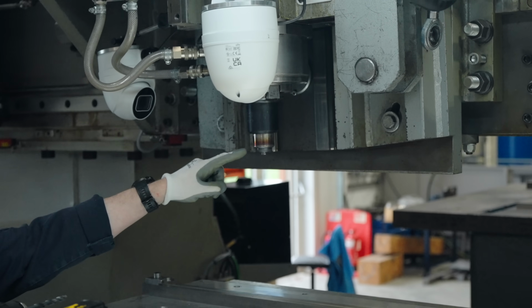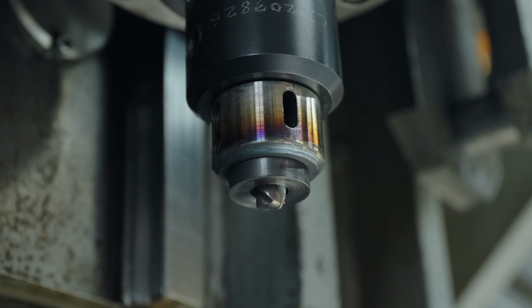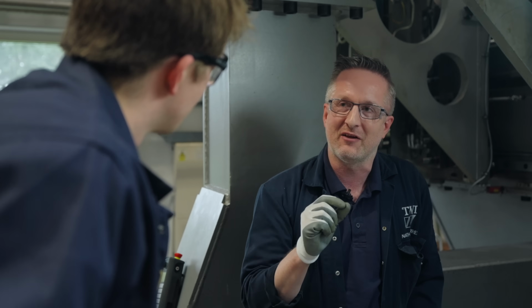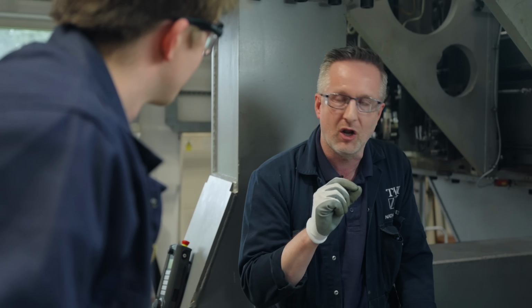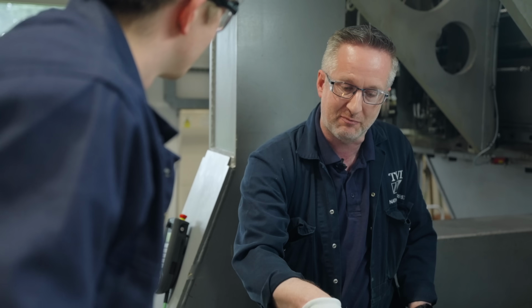So this is the tool we're going to use. This is a tungsten-based tool. The heat of the copper when we weld it is about 700 degrees C. So it's got to resist. Is that 700 degrees above the melting temperature or below the melting temperature of copper? Well, we don't actually melt. We plasticize, and we make a very, very low temperature weld, which keeps the properties of the plate intact.